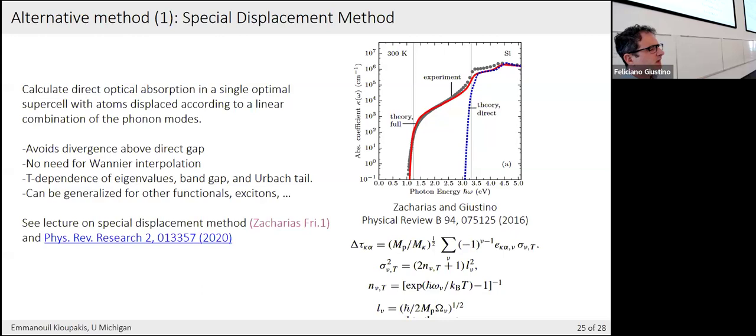Right? So if you have a doped semiconductor, you only populate a small fraction of the Brillouin zone. So there you need very fine phonon wave vectors, on the order of 100 by 100 by 100 grids. Those are easier to handle with perturbation because you just do many calculations and interpolate on this grid. With the displacement method, you need very large cells to capture these very long-range phonons. And maybe that's a case where the perturbation theory would work better for the effect.